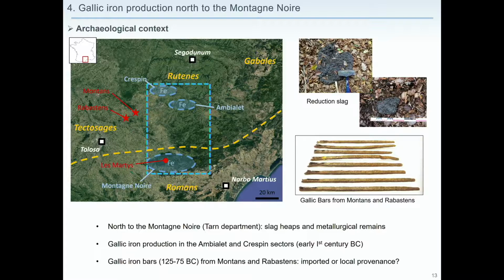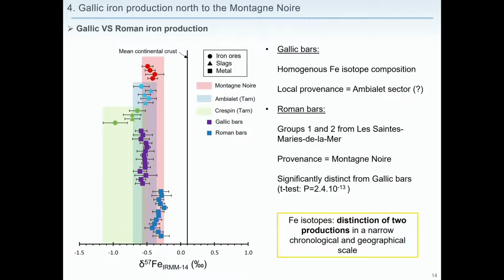These bars are from about the same period as the Roman iron production. So here are the compositions of the two Tarn sectors and the materials from the Montagne Noire. And even if there is an important overlap between these three sectors, the composition of the Gallic bars is very homogeneous and corresponds to the exact mean value of materials from this sector. So at least for this bar, we can suggest a local provenance, maybe from this sector, for the Gallic bars.